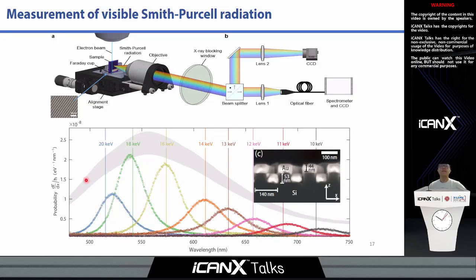The peak envelope has two reasons. Towards the long wavelengths, the reduced brightness of the electron gun will increase the electron-structure separation and thus reduce the emission probability. But towards the short wavelengths, it is the material response of both silicon and gold that reduces simultaneously, which accounts for this reduction towards the short wavelengths.